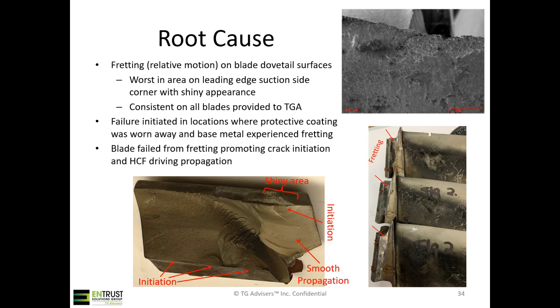So you can see the really rough appearance, especially the edge of the material there, right in the center of the image. The bottom right image, that's 3 of the blades from this engine. So those shinier areas that you can see with the red arrows pointing to them, those were the areas of greatest fretting. The fretting was worst in an area on the leading edge suction side corner of these dovetails, and one of the most important aspects was that it was consistent on all the blades, provided to TGA.